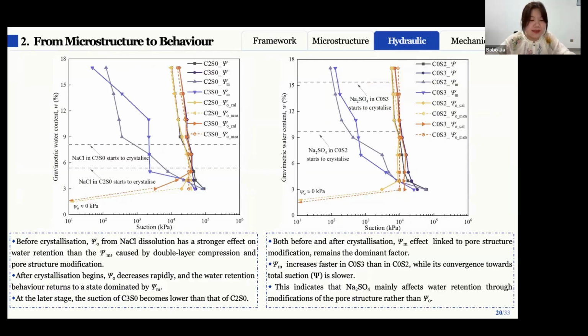And these two figures show the influence of the salt content on the drying process of water retention. For the sodium chloride samples, before crystallization, osmotic suction plays a dominant role. Dissolved sodium chloride enhances water retention. So samples with higher sodium chloride content exhibit stronger water retention capacity. At this stage, the effect of osmotic suction is greater than the matric suction.